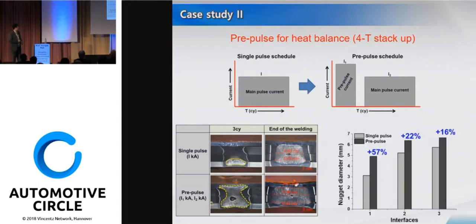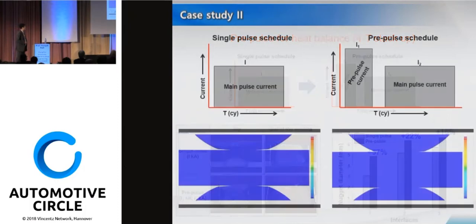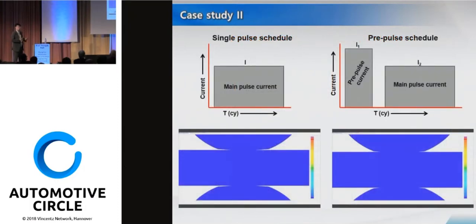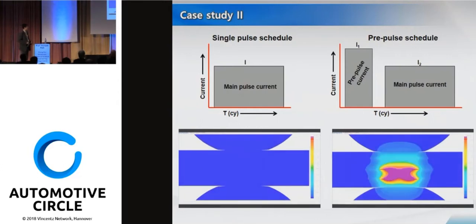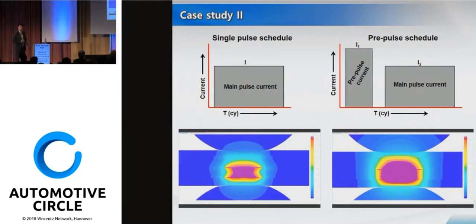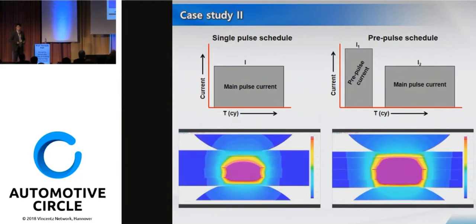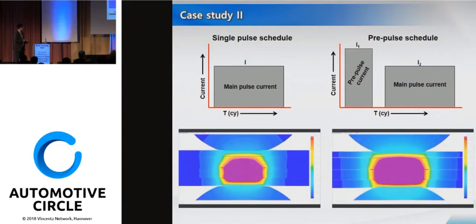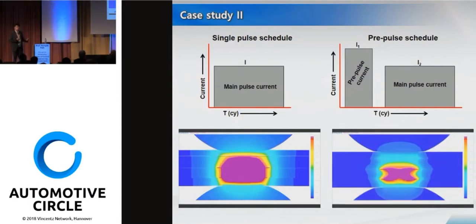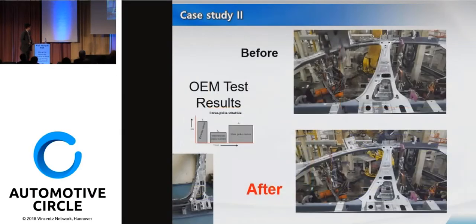So with the nugget diameter here, compared to the single pulse, with this pre-pulse schedule, pulse current profile, we improved the nugget diameter by about 57%. We wanted to validate how this works through simulation. I want you to focus on the top sheet, heat generation with the pre-pulse current. Here's our simulation. You can see that during the pre-pulse schedule, there's a large heat generation at the thin side. But in the case of a single pulse, the heat is growing, the nugget is growing, but it probably stops here. So a large difference has been validated through the simulation.